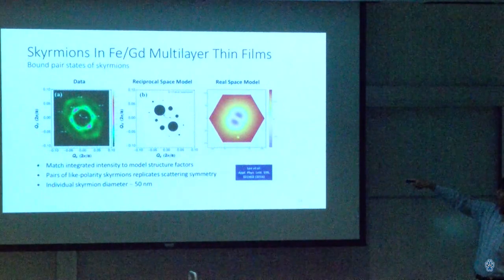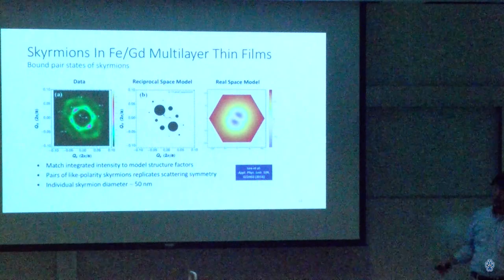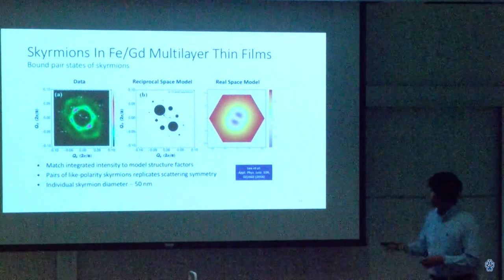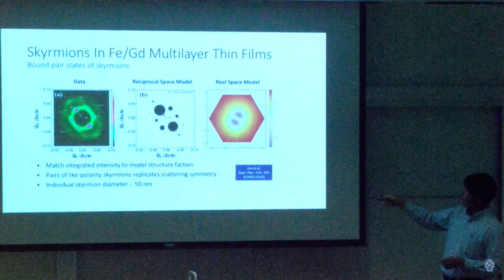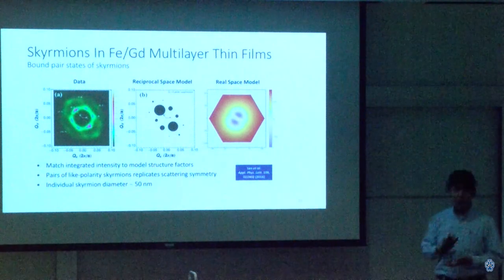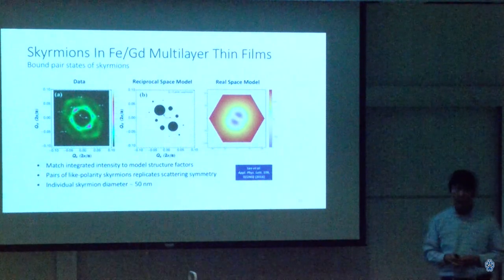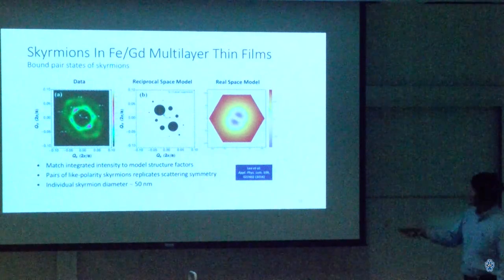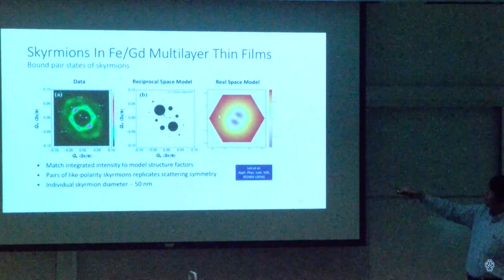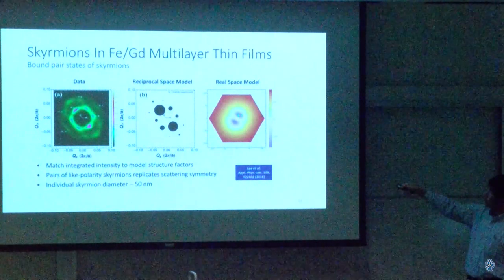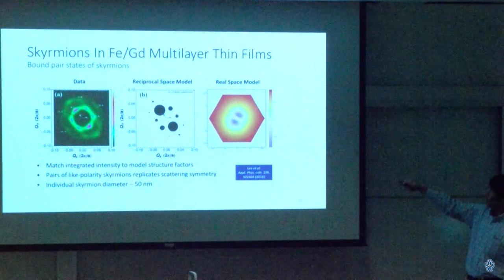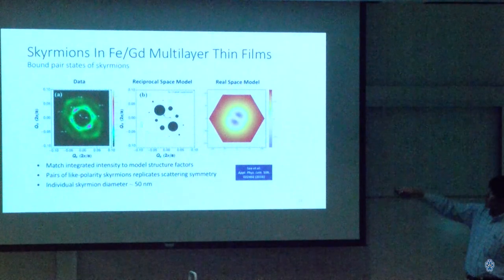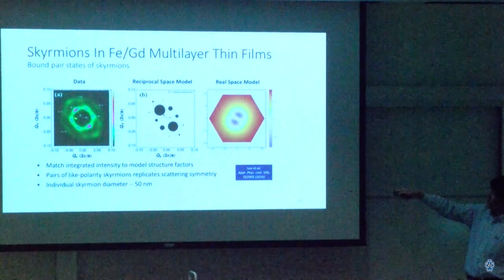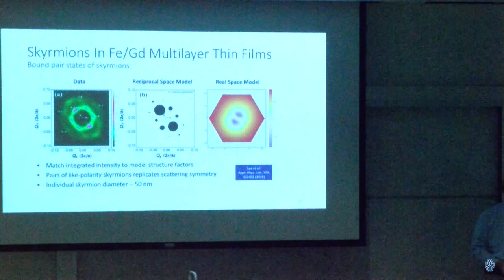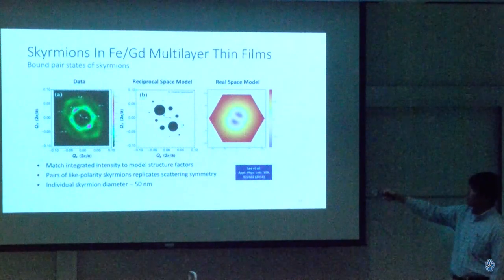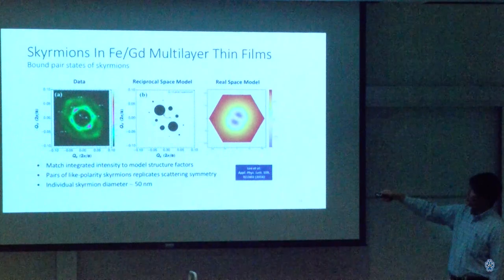by simulating how the magnetic texture looked in real space. We tried various different configurations, guided somewhat by theoretical calculations, but mostly by pure inspiration. And then ultimately what we found is that this real space model, in which you have two downward parts surrounded by an upward background, produces this model pattern that corresponds very well to the data that we saw. It has the same asymmetry, for example, and the same six-fold pattern.